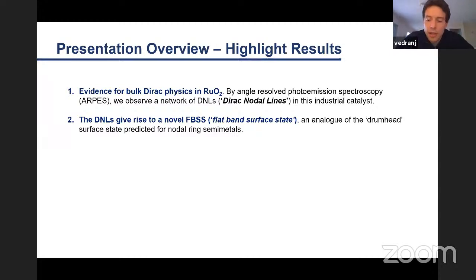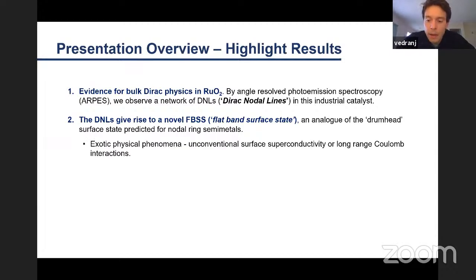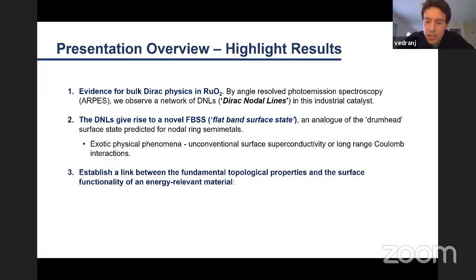It's a new gateway for the study of exotic physical phenomena, like unconventional surface superconductivity in some of these materials, or long-range Coulomb interactions. These results established for the first time a link between the fundamental topological properties and the surface functionality of a very energy-relevant material. It's a very popular, gold standard catalyst for the water splitting reaction, amongst other processes. And we will try to make a link between the Dirac nodal lines and these nested hotspots in the Fermi surface to magnetism in this material.